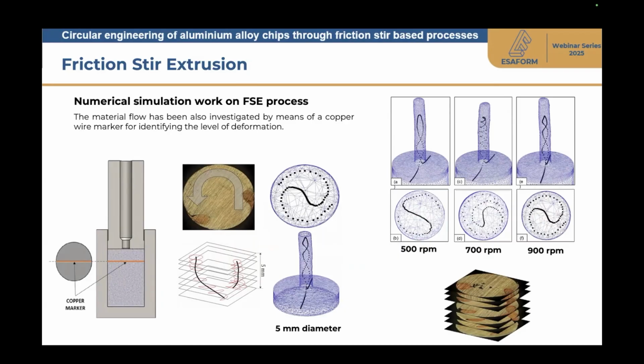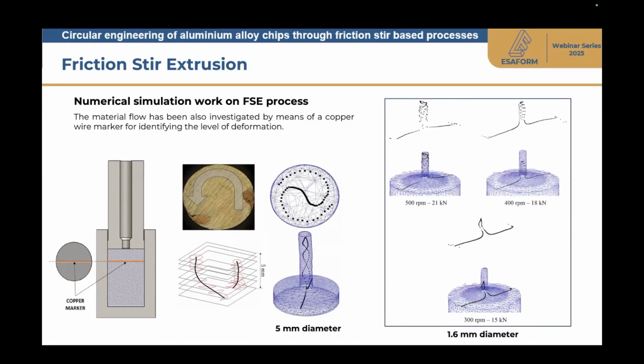Namely, the material undergoes a proper spiral movement with spires characterized by a pitch, which is strongly dependent on the tool rotating speed, on the extrusion matrix rotating speed. And in this way, at the varying of the rotating speed, but also at the varying of the extrusion ratio, different combinations, and in particular different spirals, are observed in this kind of material flow.